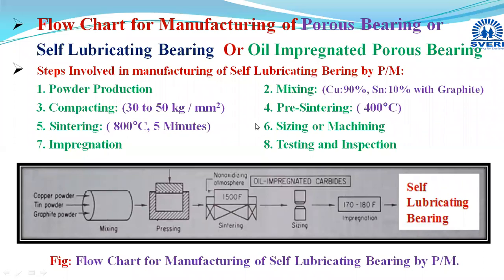Okay, so after pre-sintering, the next step is the sintering, and this is the symbol for the sintering stage. Okay, in this symbol you can mention the temperature in degrees Celsius. I have written it here in degrees Celsius. In the sintering stage, that component after the pre-sintering stage is taken and heated at 800 degrees Celsius for 5 minutes. The sintering time is very short, only 5 minutes. We are heating it at 800 degrees Celsius.